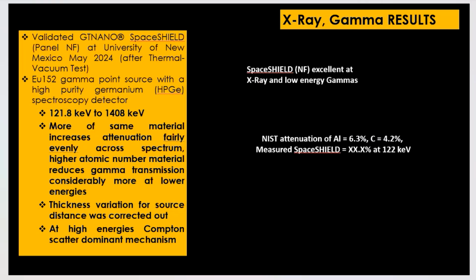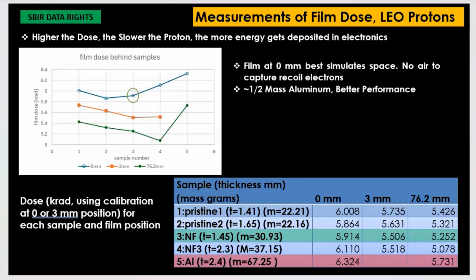Well, this chart normally has a plot on it that shows data, but since we're in a non-CUI environment, you're not going to see that. But what I can tell you is that we tested the space shielding at the University of New Mexico against a gamma source that went from about 122 keV up to 1.4 MeV. Again, our material is lighter than aluminum, but it's far more effective at stopping X-rays and gamma rays than aluminum is. Likewise, we took the material out to UC Davis to the Crocker Nuclear Facility. We hit it with high energy protons that one would see in a low Earth orbit environment. And the table indicates that the dose that we saw with our shielding was better than what aluminum would allow you.